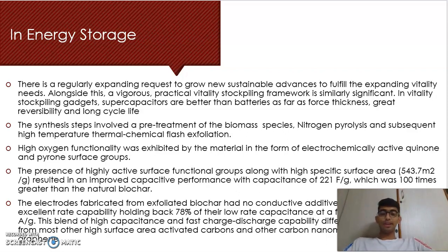The electrodes fabricated from exfoliated biochar had no conductive additives in them, and yet showed an excellent rate capability, retaining 78% of their low rate capacitance at a fast discharge value of 40 ampere per gram. This combination of high capacitance and fast charge discharge capability differentiates this material from other high surface area activated carbon and other carbon nanomaterials such as graphene.